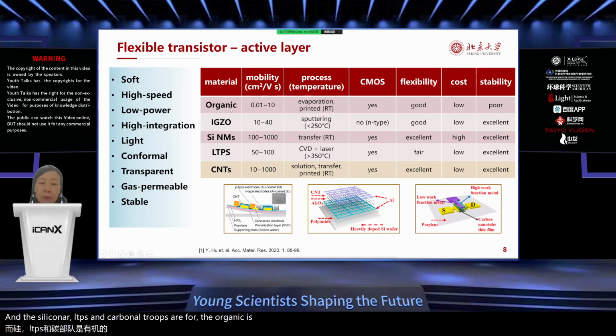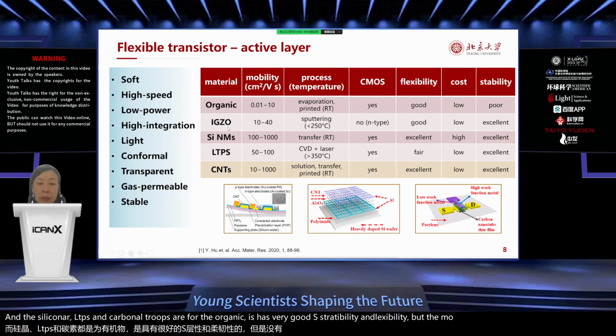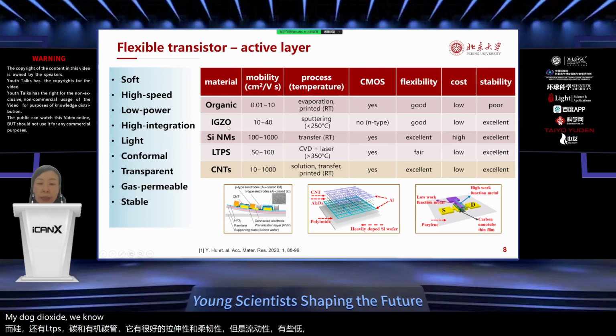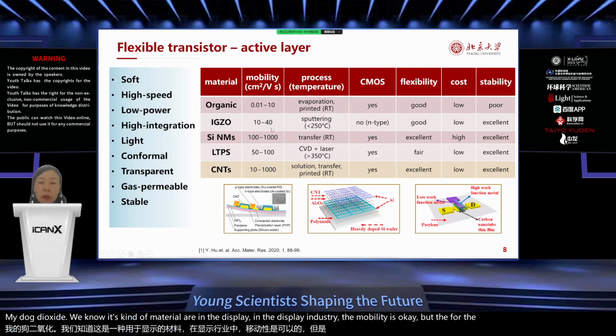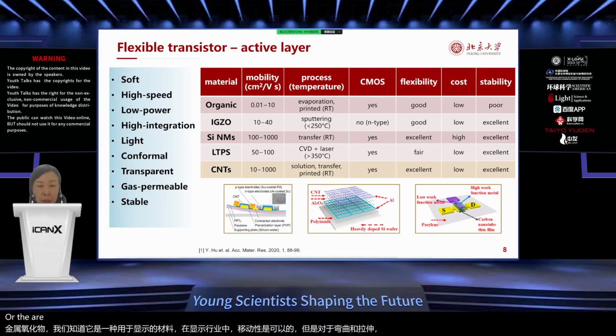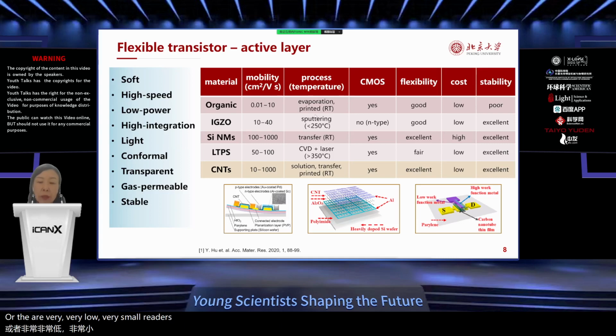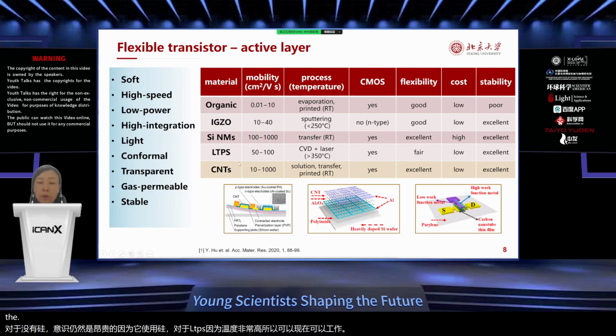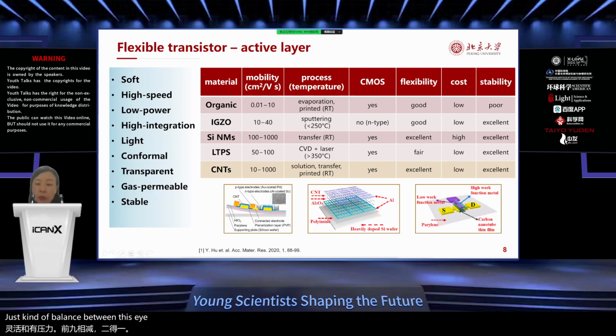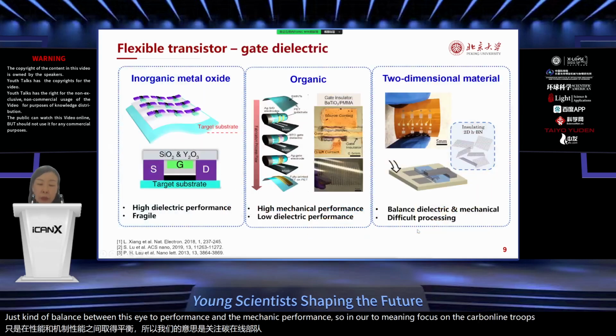For the organic, it has very good stretchability and flexibility, but the mobility is somewhat low. And the metal oxide, we know it's a kind of material in the display industry. The mobility is okay, but for bending and stretchability, for very small radius bending or the stretchable transistor, that's a problem. The silicon nanowire is still expensive because it uses silicon, and for the LTPS, because the temperature is very high, it cannot work for the flexible and the stretchable substrate. Carbon nanotube is just kind of a balance between the electrical performance and the mechanical performance. So in our work, we mainly focus on the carbon nanotube active layer.